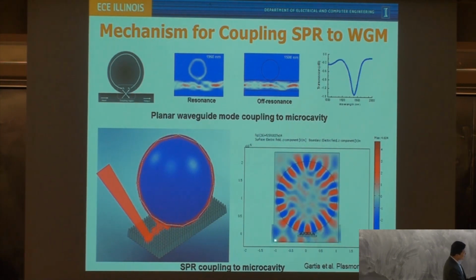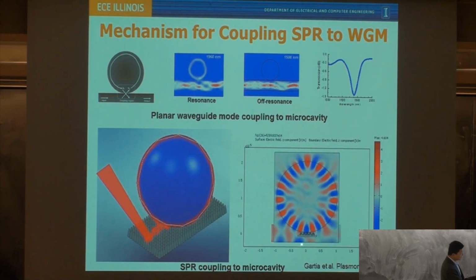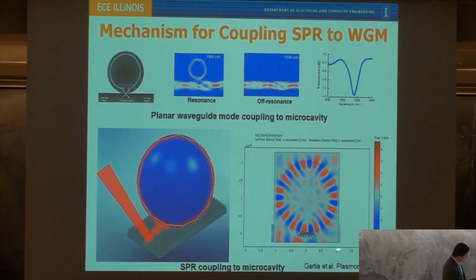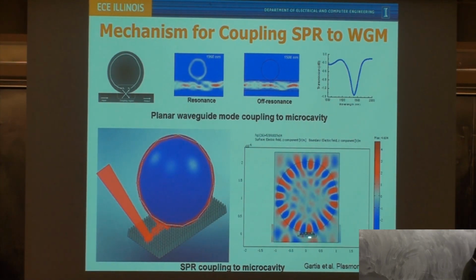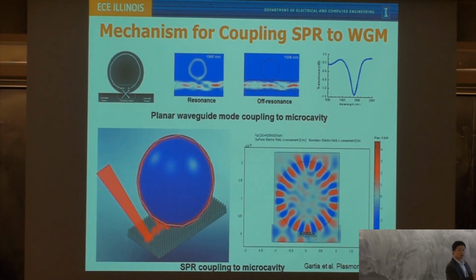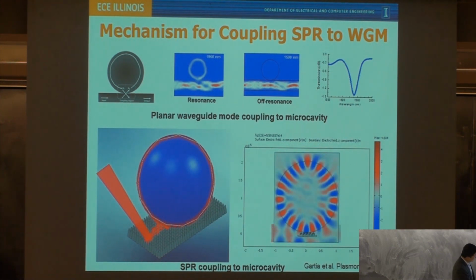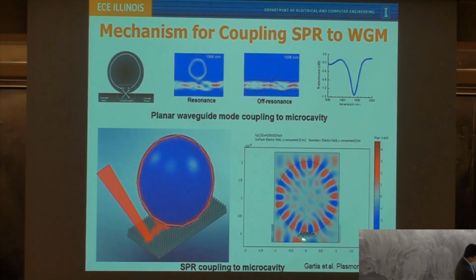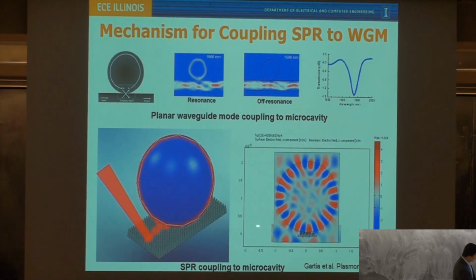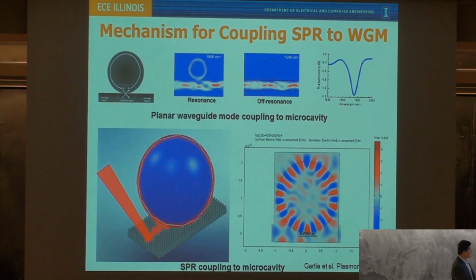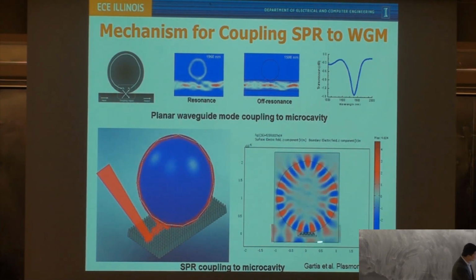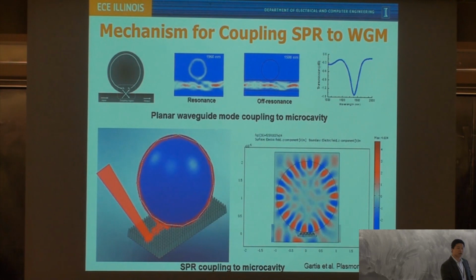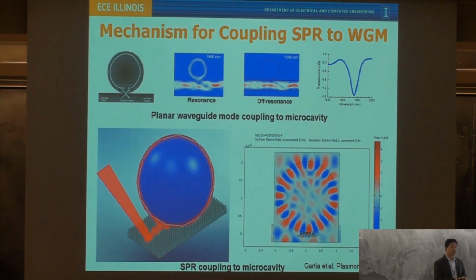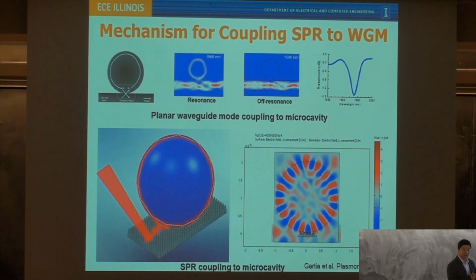Here we launch a plane wave propagating from left to right. This may be too small, but this is basically an array of a few nanoparticles connected to each other. With the help of these nanostructures, we do see light waves coupled inside this spherical cavity. If you remove them, it's not going to happen. Most people excite whispering gallery modes in a spherical cavity by using a taper fiber. They use optical fiber.